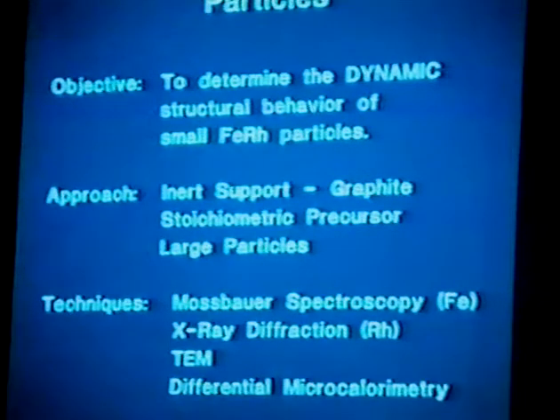The approach, as I said, was to use an inert graphite substrate, and we used a stoichiometric organic precursor compound as our starting material. In this way, we started with the stoichiometric ratio of metals in all of our metal clusters from the outset of the experiment. It was a 1-to-1 ratio of iron and rhodium. And we loaded the graphite to about 5 weight percent, which gave us large particles, and this limited some of the small particle complications in interpreting the data.